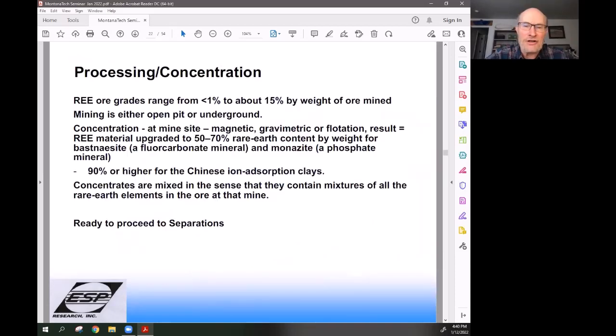And this slide really kind of feels out of place. I think we've addressed most of what's in it, but I'll repeat a couple of things. One, the ore grades come in from less than 1% to about 15% by weight at the time of mining. And you can either have open pit or underground mining. We concentrate through magnetic, gravimetric, and flotation approaches to get 50 to 70% rare earth content by weight for bastnasite, which is a fluorocarbonate. And monazite is a phosphate mineral, which we tend not to process much lately these days, or haven't traditionally done, because monazite tends to contain more of the radioactive materials. And then I indicate the 90% you find when you process the ion absorption clays in China.